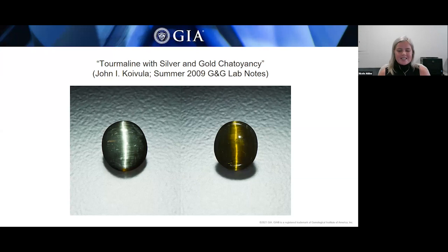Pictured here is a 5.44 carat double cabochon, and it's displaying a silver cat's eye on one side and a golden eye of almost equal intensity and sharpness on the other. Microscopic examination revealed a strong color zone of brownish yellow, parallel to a near colorless zone. That near colorless zone contained very fine, uniformly distributed growth tubes, responsible for the silvery white eye seen on the left.